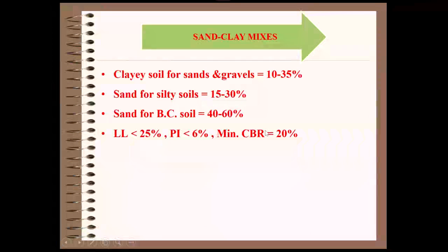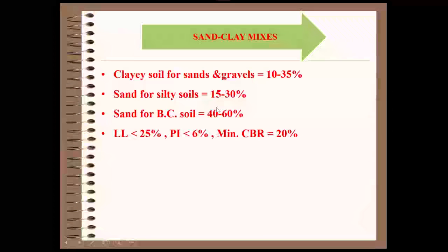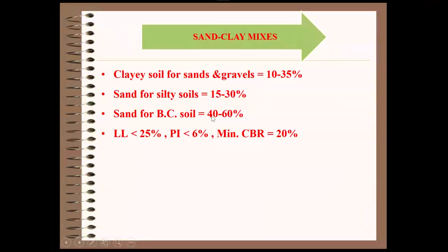And moreover, see the stringent guideline here, liquid limit should be less than 25, plastic index should be less than 6, minimum CBR 20%. Even if we do all this, there is no guarantee that we will get this specification satisfied. For example, here you see 40 to 60% of the sand you might have added, say. But then the whole problem is the remaining 40% is clay. That clay, 40% clay is very high to control the remaining 60%.